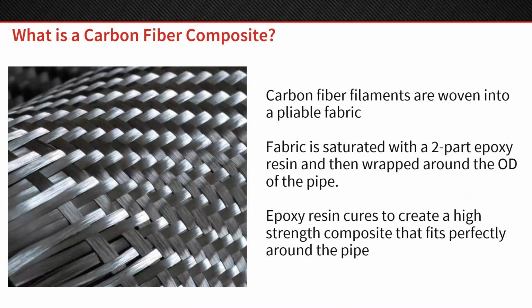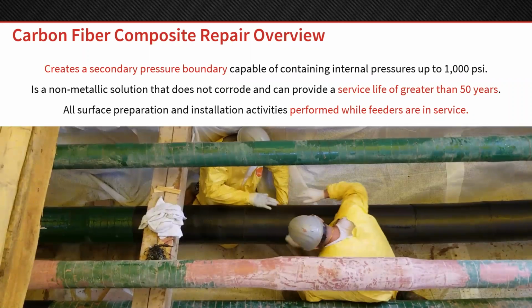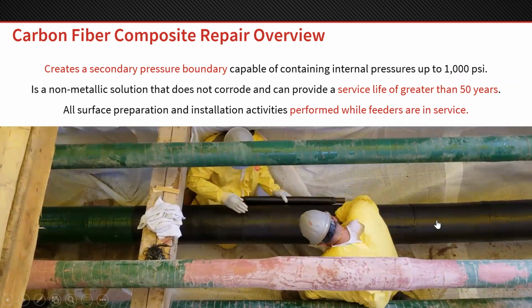So what is a carbon fiber composite? Let's kind of dive into that. The basics of it, we take carbon fiber filaments, they're woven into a pliable fabric that you can see here. This fabric is saturated with a 2-part epoxy resin, and then it's wrapped around the OD of the pipe. The resin cures through a chemical cross-linking mechanism, and it creates a hard, strong composite that fits perfectly around the outside of the pipe. You can see a repair in action right here.